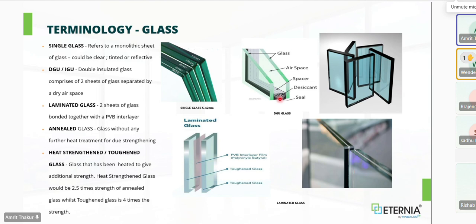It is always recommended, whenever you are taking the thickness of the glass, you need to 2x the size of your spacer. Meaning if you are taking 5 mm glass, you need a minimum 10 mm spacer. If you are using 6 mm, you need a minimum 12 mm spacer. For 8, you will need a minimum 16 mm spacer. So always the glass thickness into 2 is the spacer thickness. In most cases I have seen the glasses wrongly selected by the dealers. They are selecting 5 with 8, 6 with 8. 8 is not the correct spacer selection. Always use a minimum 10 mm spacer or go with 12 mm. So that is more important to understand.